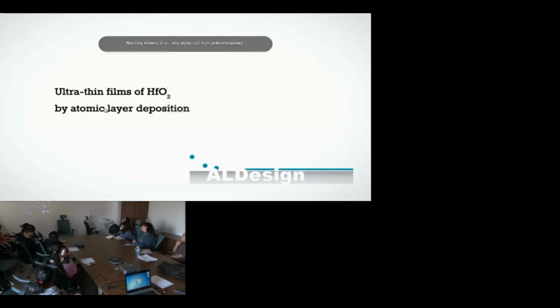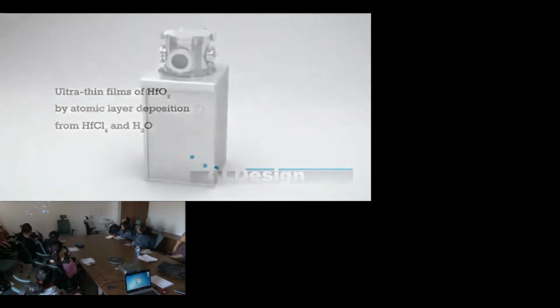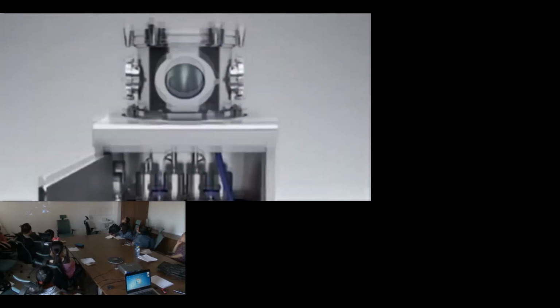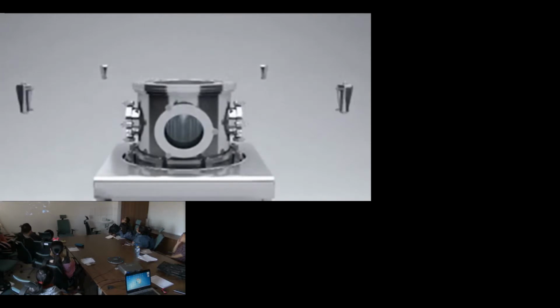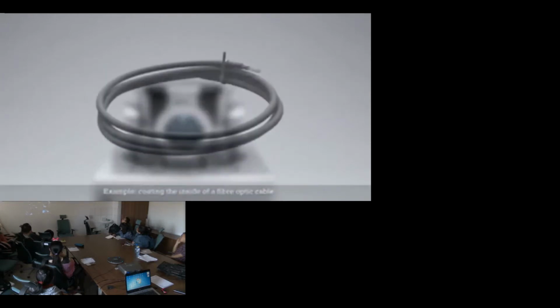Okay, so this will show how ultra-thin films of hafnium oxide can be formed by atomic layer deposition from the gas phase using hafnium chloride and water. So here you have the precursors, and here is the reactor chamber. It's very similar to ours.